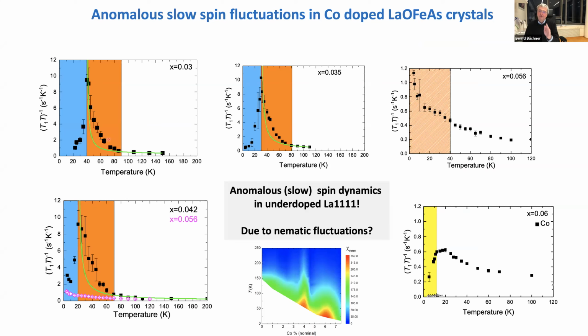On the other hand, it is really challenging to get the crystals, and I think it's too early for me to say whether this is crystal-dependent or intrinsic. This I don't know. But from the NMR, if you look in the paper which is on the arXiv, you see there is a region in the phase diagram where we see some kind of short-range phenomena. Is it commensurate or incommensurate? Well, NMR probably doesn't know. I have no idea. So at the moment we have these NMR data. As far as I know, at least for our crystals, there's no neutron data yet.